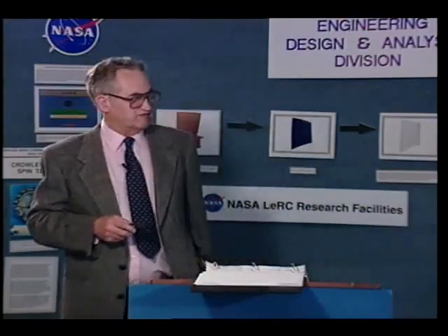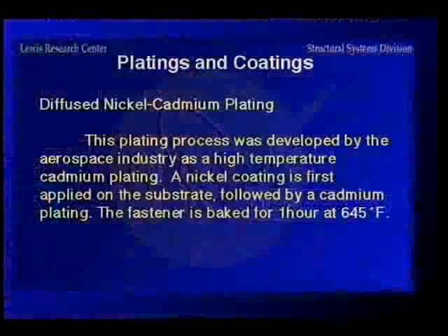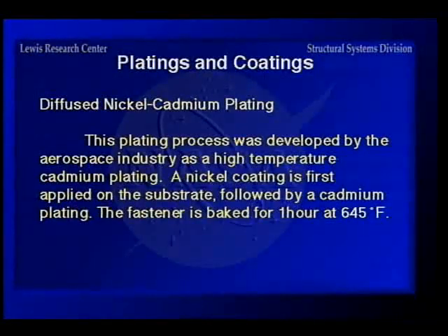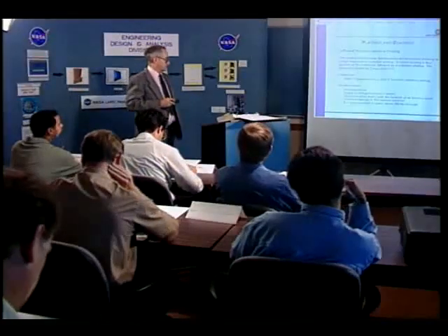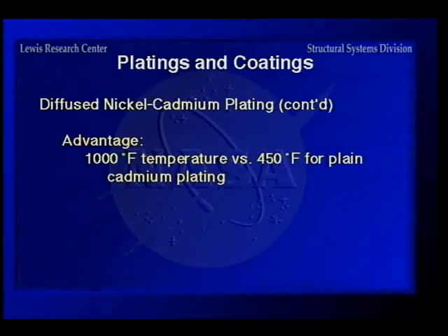Diffused nickel cadmium is another one that was developed by the aerospace industry as a high temperature cadmium plating. And you put a nickel coating on first, and then put cadmium on over it, and bake it for 1 hour at 645 degrees. Now the advantage, you can get up to about 1,000 degrees exposure temperature, which is good, versus 450 for plain cadmium plating.